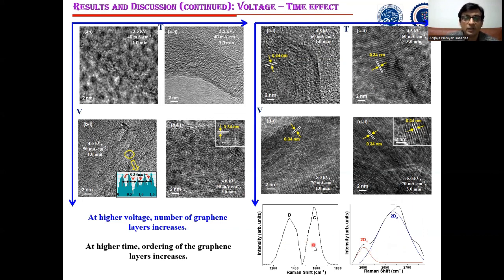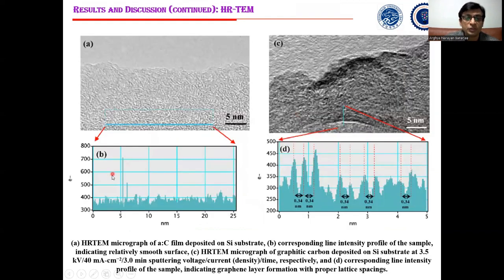And this is the D and G peak, which is typical of the carbon network. And what we observed is that when we increase the sputtering voltage, the number of graphene layers increases. On the other hand, when we increase the sputtering time, the ordering of the graphene layers increases. Here you can clearly see that in the multi-layer graphene, with increasing sputtering time, highly ordered graphene layers are created, and when we increase the sputtering voltage, the number of graphene layers increases. And this is showing the typical line intensity spectra to show the proper d-spacings, actually corroborating the proper graphene layer formation.